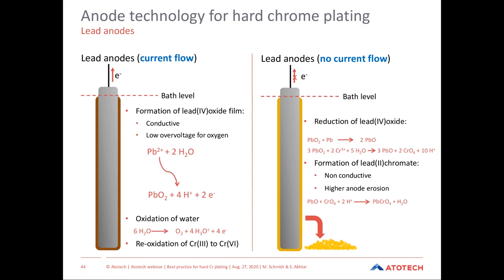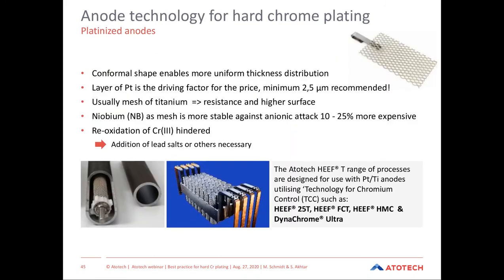On the lead anodes, there is typically a lead dioxide layer formed during the plating. You see this on the left side. On this layer, typically the reoxidation of trivalent to hexavalent chrome is happening. In idle times, this layer is destroyed by the chrome bath, and if the anodes are very long in the solution without current, lead chromate can form, which will also reduce the shape or the diameter of the anodes. For that reason, nowadays the industry tends also to move over to platinized titanium anodes.